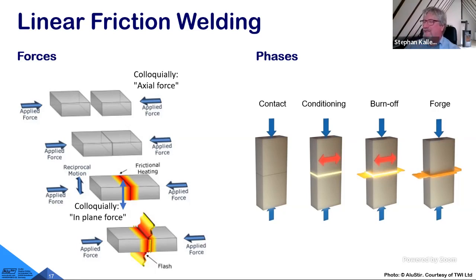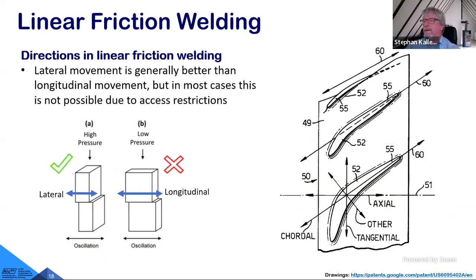You see 4 different phases: initial contact phase, where the material just gets hot by friction, and then conditioning. So the spikes of the material have already been worn out, and now we have a sliding contact within the burn-off phase with a plasticized layer in between. The flash is being generated, and then we stop the reciprocating motion. You see the red arrow disappears, and the 2 parts are carefully aligned against each other, and the forging force is applied. This is typically at least 20 or even 50% higher than what we use during the reciprocation.